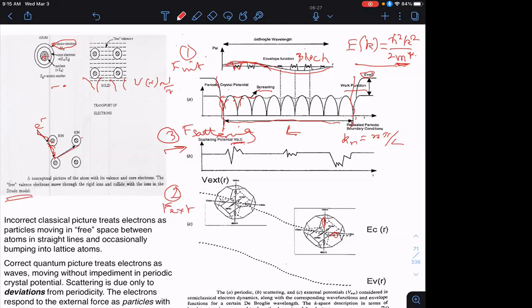So what I'm saying is if you launch an electron in a perfectly periodic potential, as you see in a perfect crystal, you will not encounter any collisions or scattering of the electrons with the perfectly periodic atoms. Instead, you have to think of this electron now as a wave, which kind of surfs effortlessly through this perfectly periodic arrangement of atoms. And all that the periodic forces of the crystal will do is change the actual electron mass m0 into a new modified mass m star. And that's what comes out of the solution of the Schrodinger equation. Once you use the effective mass, you should ignore the periodic crystalline forces anymore because that will be sort of double counting the impact of the periodic crystalline forces, okay? So now these particles with an effective mass can only undergo scattering if there are any deviations from this perfectly periodic crystalline potential. And that, of course, is a huge conceptual leap, okay?